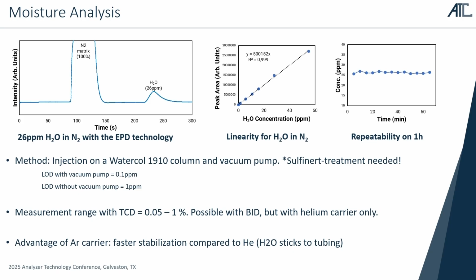Also, this example here was acquired for moisture by GC, and for this application we had to use a Watercol 1910, which is a very specific column from Millipore Sigma, and we were able to reach a 0.1 ppm limit of detection for moisture with the use of a vacuum pump at the end of the detector. This is much more sensitive than what has been done by other companies that use the TCD for measuring moisture with this column, who showed a limit of detection around 0.05 to 1%.